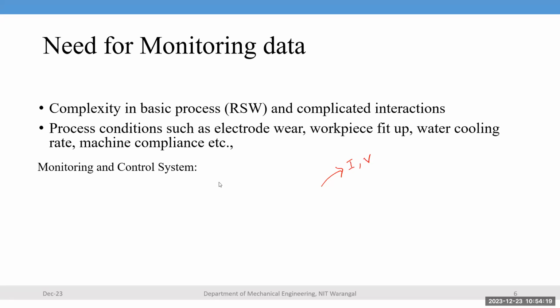Then workpiece fit-up and water cooling rate, because you are circulating the water to reduce the heat accumulation in the electrode material. Then machine compliance, because you are applying the force and other parameters, so what is the compliance of the machine. Then electric current, voltage, displacement and dynamic resistance signals, because you are supplying the current and voltage during the process so that heat is generated. So that heat is utilized to melt the two adjacent materials.